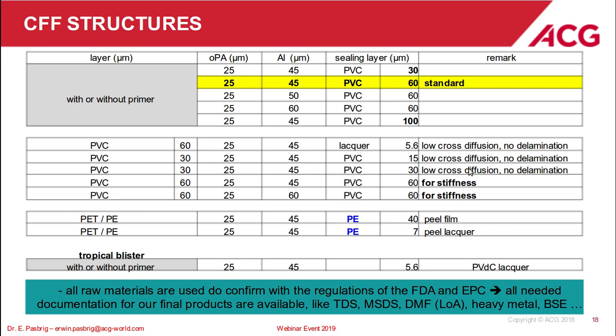The last two materials in this row are used for stiffness and for flatness as well. So we have 60 micrometer PVC in the first part, and in the last laminate in this part of the table, you have 60 PVC, 60 aluminum, and 60 PVC. It's a very stiff material and has a very good flatness.